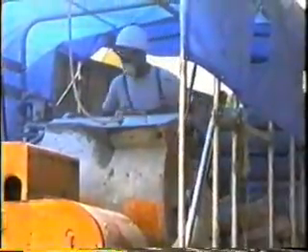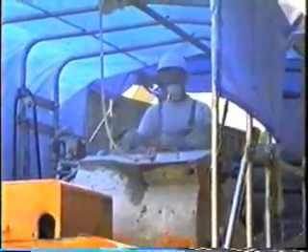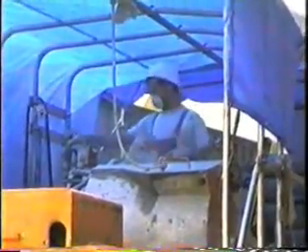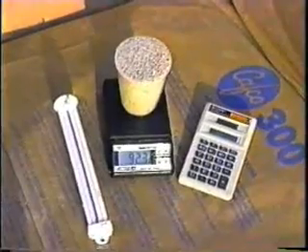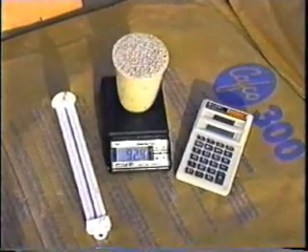The proper amount of water and mix are crucial to the successful installation of wet mix materials. Therefore, the mixing area should be equipped with both a clock and water metering device to ensure that a constant water quantity per mix and water to product ratio are maintained. Mixer and nozzle density should be checked periodically to ensure that the optimum performance of the material is being achieved.